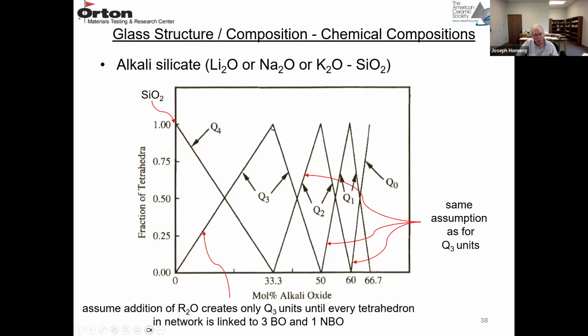So now you have 100% Q3 units, 0% Q4 units, and then you start forming the Q2 units, and that'll reach 100% as the Q3 units decrease. Then you start forming the Q1 units, and the Q2 units decrease. And finally, you form the Q0 units as the Q1 units decrease. So this assumption, that you create only Q3 units until all the tetrahedron units in the network are linked to 3 bridging oxygens and 1 non-bridging oxygen, is the same assumption for all of these as they create the different types of units.